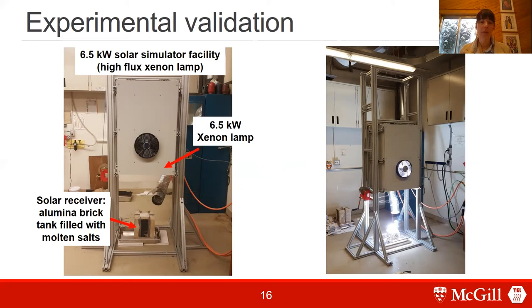And another thing that we're working on is developing lower cost tank materials, which I'm going to discuss in a moment. So here you can see this is our experimental facility. We have what we call a solar simulator, which consists of a 6.5 kilowatt xenon lamp. This xenon lamp has reflectors inside, and it can focus the light onto a receiver, which is located here at the bottom. In this case, we have a little receiver that's like a tank made of alumina bricks, and it's filled with chloride salts. And you can see what it looks like when it's turned on. So we use this light to melt the salts, and then we have temperature probes to study the thermal behavior of the chloride salts. So those are the experiments that we're running for the chloride salts.